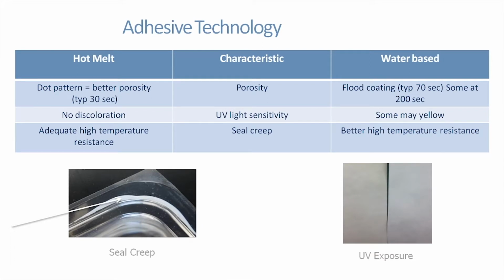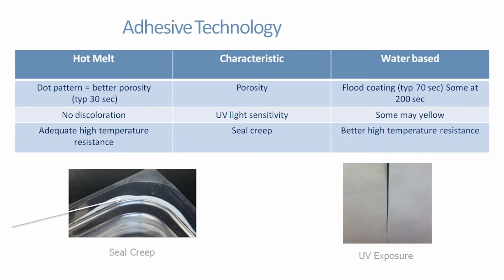Three more characteristics. Porosity. Jose alluded to that a little bit. Think about hot melt and those dots, and in between the dots you've got open area. So from a porosity standpoint, hot melt is almost always going to be more porous than a water-based system that's going to be flood coated. If you look at Gurley Hill seconds, that's the amount of time to get through the substrate. Lower is better. It means it's more breathable. For ETO sterilization cycles, you're going to get the gas in, the gas back out, get your residuals out faster with a hot melt process versus a water-based.